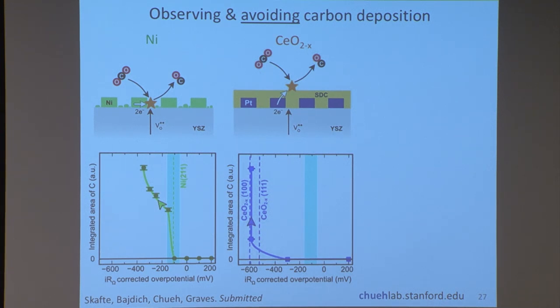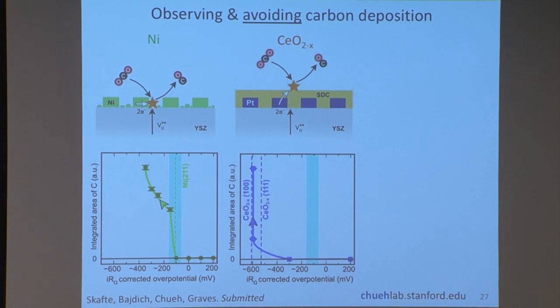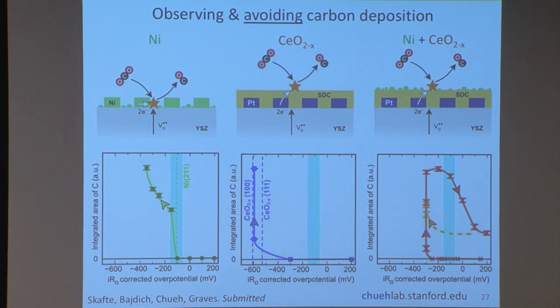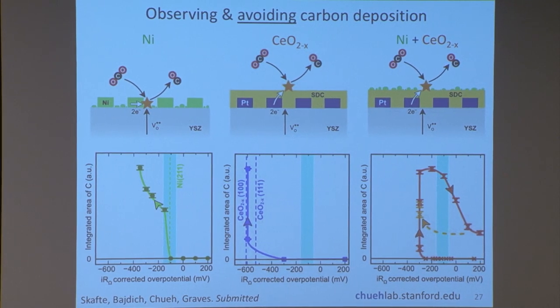But the problem here is that it's not very good for the first reaction, so the efficiency is low. So what people usually do is you take both and you put it together. And that's what we have done here, is to combine the nickel catalyst with the cerium oxide catalyst, and you make a composite, and that's what's shown there.